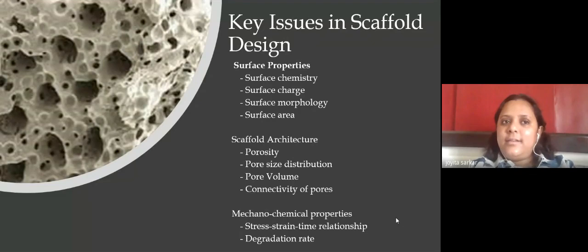So this is such an interesting phenomenon which occurs in the liver cells, that within the range of a few, let's say 2 to 20 kilopascals, you could get different cell functionality. For hepatocytes, the lower the compressive moduli, the better. For stem cell differentiation into hepatocyte, the higher the compressive moduli, the better.